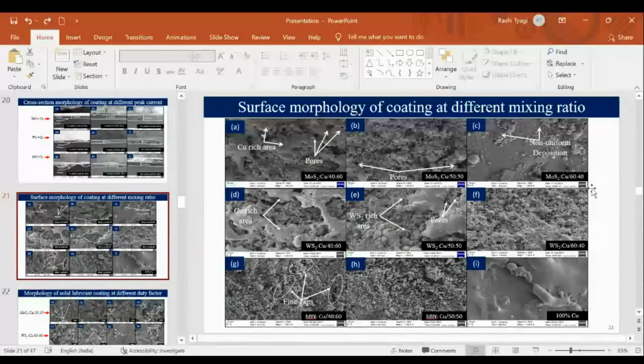We have observed the effect of mixing ratio by changing the ratio of the powder, such as when MoS2 is high and copper is low, or copper is high and MoS2 is low. In this process of analyzing the surface morphology, we observed that there is a non-uniform deposition over the workpiece surface. It can be observed as non-uniform deposition when the MoS2 percentage is high.